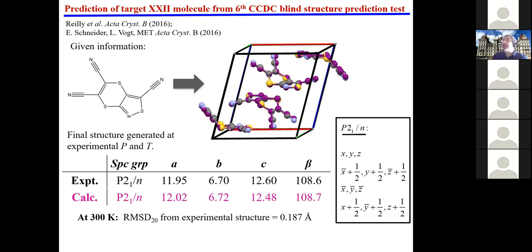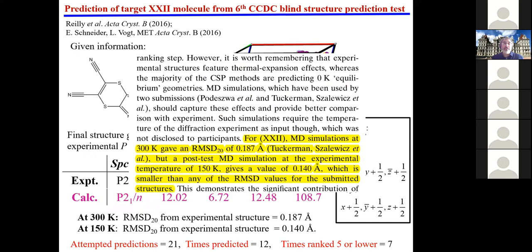It actually turns out that this experiment was done at 150 Kelvin. They never told us what the experimental temperature was at the outset of the competition. But at 150 Kelvin, the RMSD20 is 0.14, which, for this prediction, is really good. In fact, they mentioned this in the paper that came out on this, which is that when you do things at the right temperature, you get an RMSD20 of 0.14, which in this case turned out to be the lowest of all the RMSD20 values submitted.